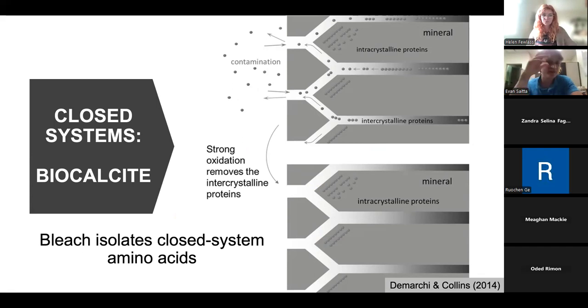Well, luckily, a lot of my colleagues have done a lot of the legwork here, and in fact, some of them might be listening to this talk right now. But biocalcite appears to be able to act as a very good closed system to trap original peptides and definitely original amino acids. And what's also very exciting is that methodologically, by applying an oxidative bleach treatment to biocalcites such as mollusk shell or bird eggshell, you can actually remove any proteinaceous material that is outside of those calcite crystals and could be contamination, and then examine only the intracrystalline fraction of the proteinaceous material within these samples. And so you can be more confident that you're not examining contamination.